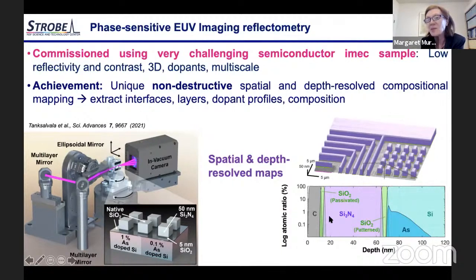So the carbon contamination, the silicon nitride nanostructures, the oxide layers, the silicon underneath, and the doping profile. This is in log atomic ratio scale. And the nice thing about this is a relatively large area map. We validated this imaging using the beautiful capabilities of electron imaging and atomic force microscopy.